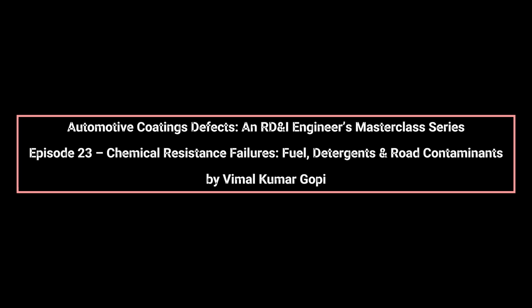Fuel resistance is one of the most critical benchmarks because fuels are complex chemical mixtures, not single solvents. Modern fuels contain aromatics, alcohols, oxygenates, and additives that aggressively interact with clear coat and base coat chemistries. When fuel contacts a coating, especially at warm surface temperatures, it attempts to diffuse into the polymer network. If crosslink density is low or polarity is mismatched, fuel components penetrate, swell the film, and extract low molecular weight species. Early-stage fuel attack appears as temporary softening or loss of gloss.